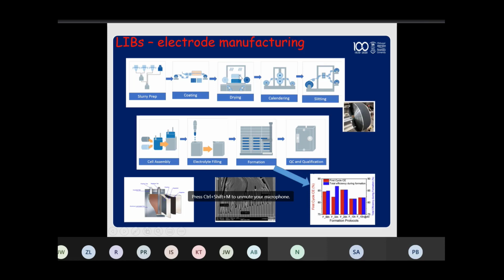After that, we dry. Drying, we remove the solvent. Again, this is one of those steps that is essential to minimize degradation and to enhance performance. That's because the various parameters that you use, temperature, time, airflow, and so on and so forth, all influence the microstructure, so the porosity of your electrode and the tortuosity, so the channels through which the lithium ions can diffuse. So these are again parameters that need to be optimized.